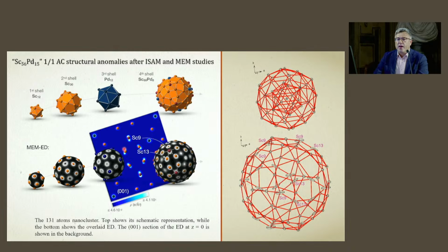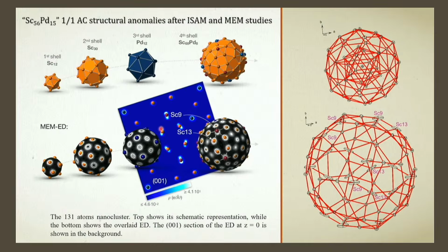We proceeded further. We used the maximum entropy method to reconstruct good quality electron density maps. As was already highlighted in the first shells, we have very sharp and spherical peaks for electron densities, but some problems become obvious in the outer shell of our clusters.